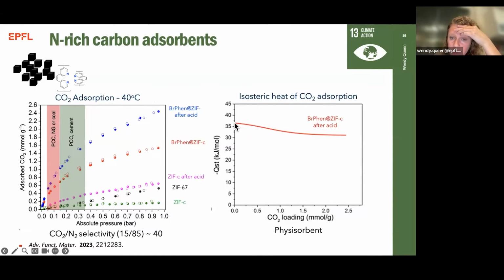And so here you can see the isosteric heat, which is the average binding energy at constant coverage. Note that it's just above 35 kilojoules per mole, which again implies that it's in the physisorption-based regime. So it's not binding CO2 super strongly.